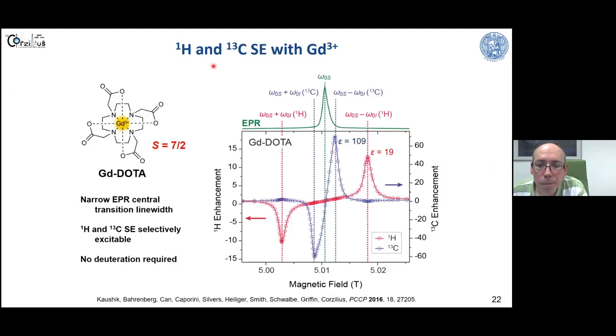We can also utilize gadolinium DOTA, for example, to hyperpolarize directly carbon or also nitrogen. I can show you in one of the following slides. And here we can achieve much, much larger enhancement factors of about 100. And with nitrogen, we have achieved something like 400, which we assume. It's difficult then to measure the off signal, actually.